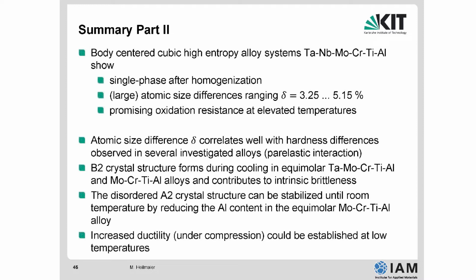I have shown you that there could be a very large atomic size difference ranging up to 5%, which is really huge, which can give rise to high strength levels. Promising oxidation resistance at high temperatures. The atomic size difference correlates well with the hardness difference. B2 forms in these alloys, which is not good.